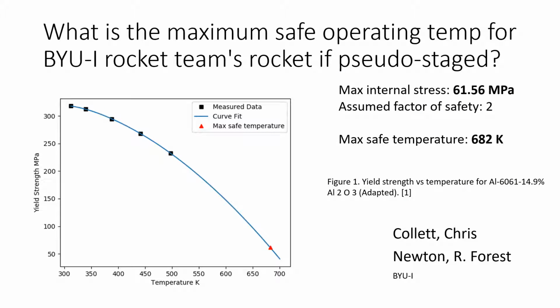To understand the reasonable limits of the aluminum in the motor casing, this graph from ResearchGate was extrapolated using a cubic spline to determine the maximum safe operating temperature. Temperature affects the yield strength of metals, decreasing it with increasing temperatures. The maximum stress that will be experienced by the aluminum casing is 61.56 megapascals. The temperature at which the yield strength of the aluminum is 61.56 megapascals is 682 Kelvin, making this the maximum safe operating temperature.